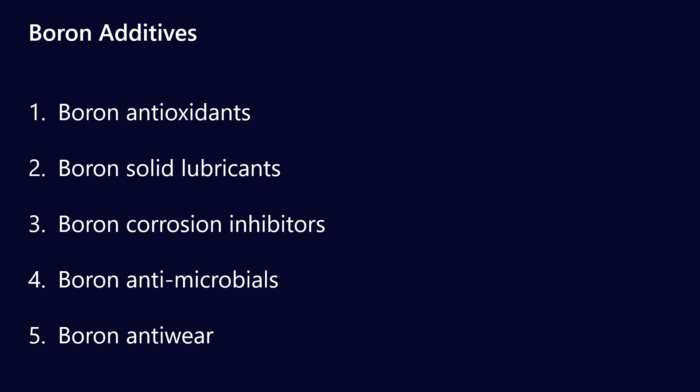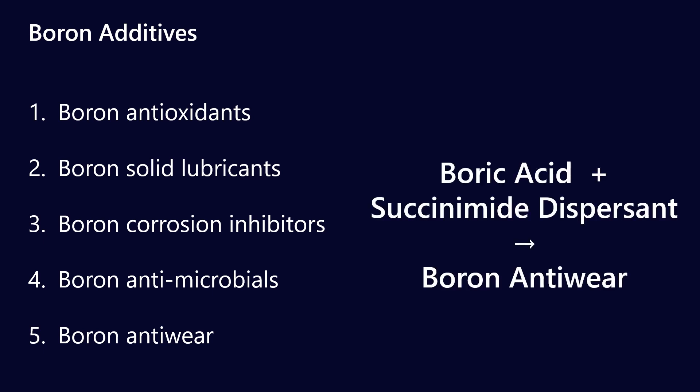Finally we've got boron as an anti-wear additive. The most common of these is when you react a boric acid with a dispersant, giving you boron anti-wear additives. What seems to happen is that at the interface, in the load zone, these additives liberate insoluble boric acid in crystalline form, which acts as a kind of EP or sacrificial anti-wear additive, very similar to ZDDP. Boron anti-wear additives are quite popular specifically in engine oils, so you'll often see boron in those formulations.